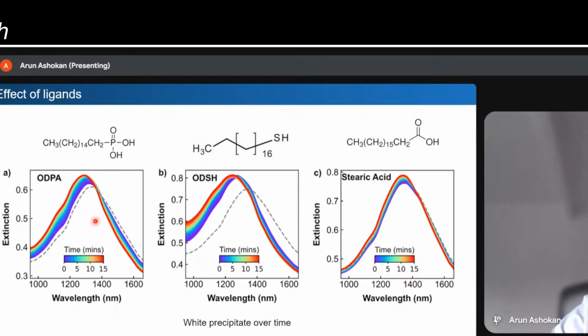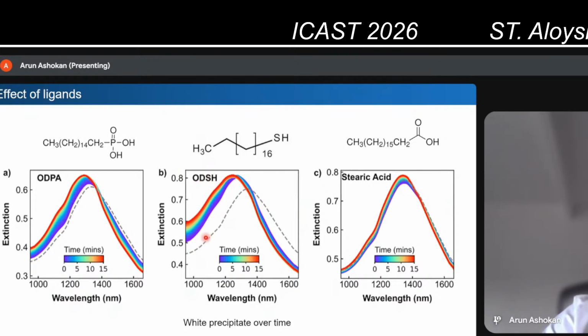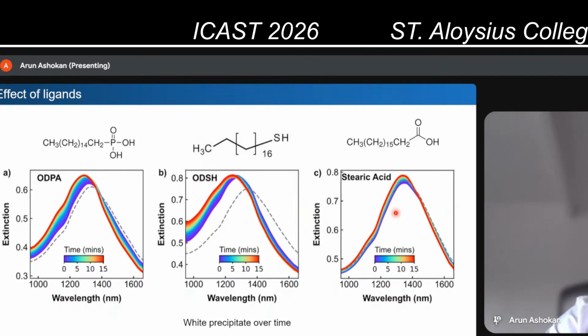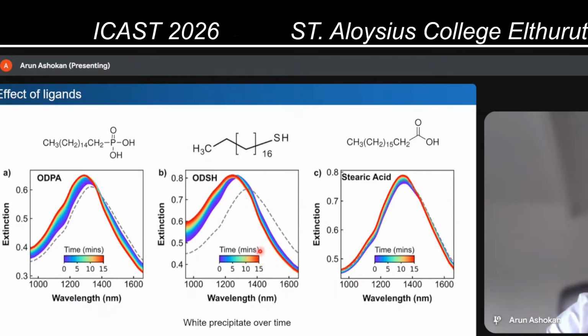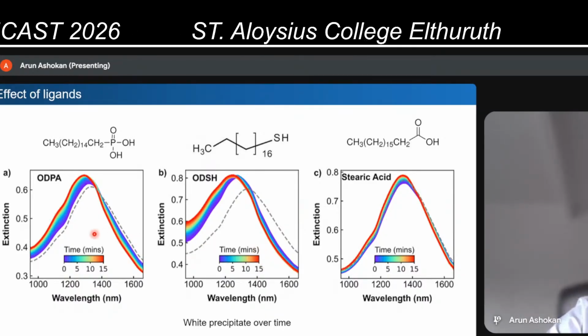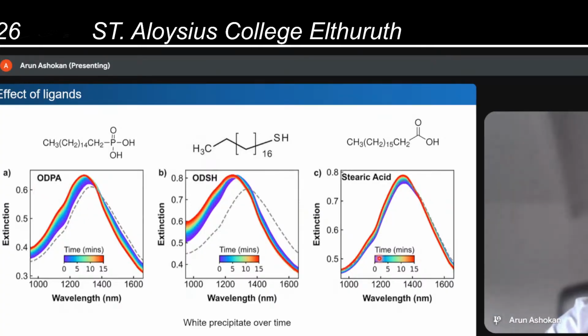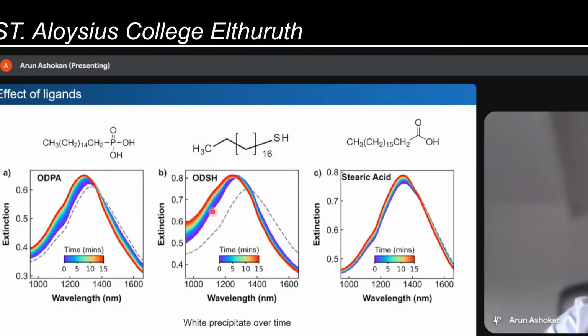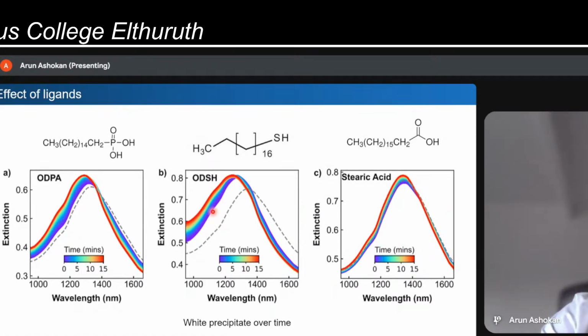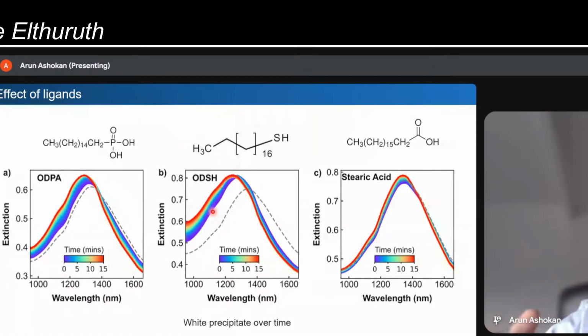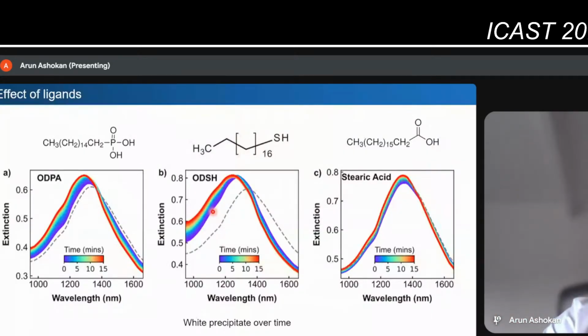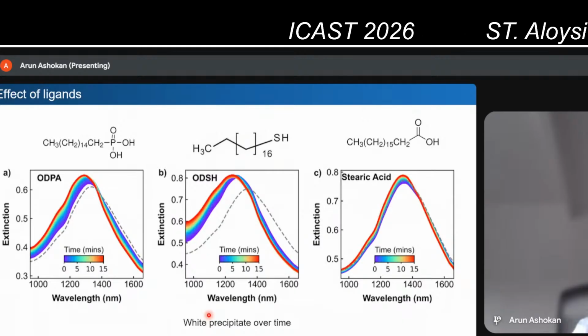Over time, it's blue shifting for all ligands. The blue shift is really large for the thiol molecules, but it's very minimal for the stearic acid. So this suggests that there is something happening. And further, there is not much change in the color of the solution for the phosphonic acid as well as the stearic acid. But in the case of thiol molecules, when you add thiol molecules, what you observe is the black color solution slowly changing its color, turning into a light yellow color, and formation of a white precipitate over time. So there is some chemistry happening there with just thiol molecules.